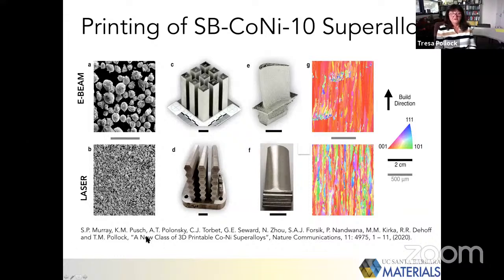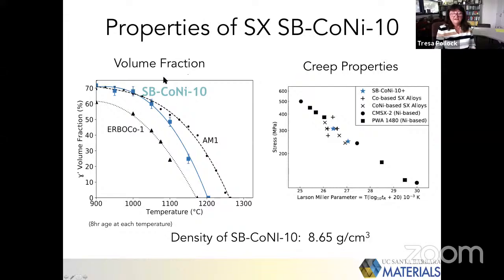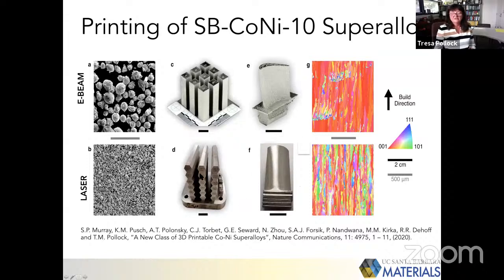And we did procure a batch of powder from Carpenter Technology, and basically separated into size distributions appropriate for printing by electron beams and by laser powder bed. And I show here some preliminary print trials where we're looking at processing conditions and printing bars where we can test properties. And we've also printed some artifacts that look a little bit like turbine blades. And you can see that we've been able to print these without any cracking. And so I think this is the first instance of a material which has this very high volume fraction of strengthening precipitates that is printable both from the perspective of simple objects, but also more complex shapes.